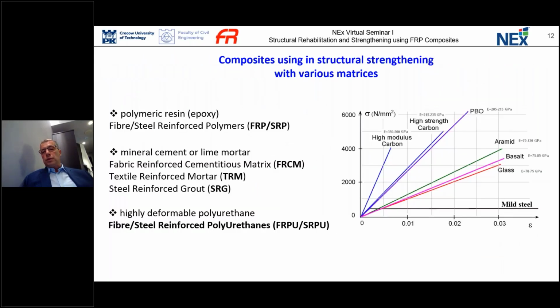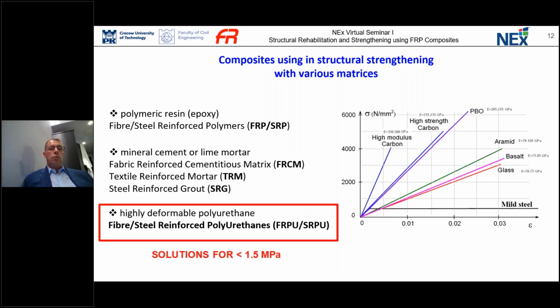So nowadays, we typically use polymeric resin, mainly epoxy, in fiber and steel reinforced polymers. Also, in the last 20 years, we use mineral cement or lime mortar as a matrix in strengthening of structures. In this case, we use fabric reinforced cementitious matrix, FRCM, textile reinforced mortar, TRM, or steel reinforced grout, SRG. Also, it is now available to use highly deformable polyurethanes, fiber or steel reinforced polyurethanes, and this kind of solution is suitable for strengthening of materials, mainly concrete or also masonry, when the tensile strength of this substrate is very low, I mean under 1.5 megapascal.